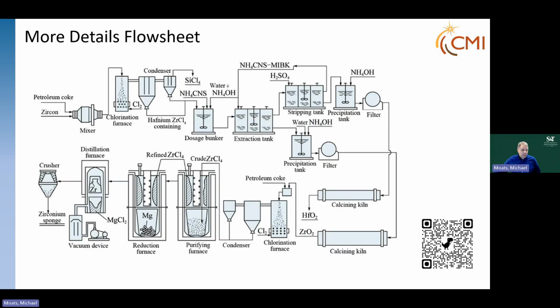More details about the flow sheet that we're going to talk about. This is what's being done in Oregon and Utah: basically, zircon is mixed with petroleum coke and put into fluidized bed reactors where chlorine gas is the reactant and the fluidizer. Hafnium zirconium chloride comes off as a gas, goes through condensers, and basically comes out as a solid. It's kind of interesting chemistry that there is not a stable liquid phase, so it immediately goes from gas to solid. Silicon tetrachloride also forms as a gas from the zircon. Its condensing point is much lower, and so it actually condenses out as a liquid eventually.